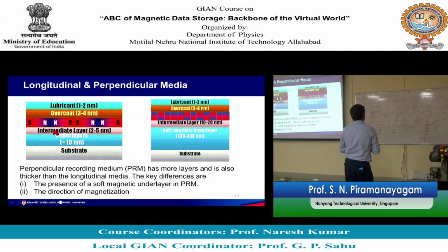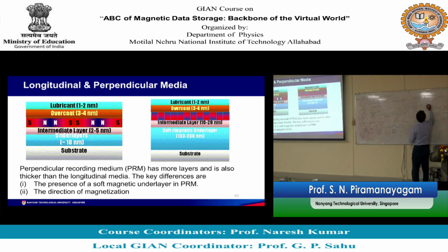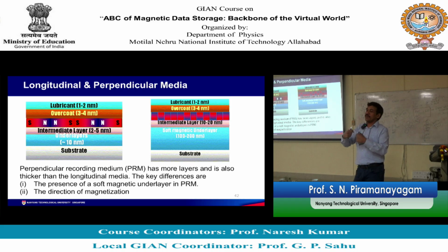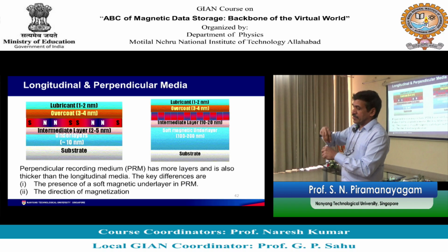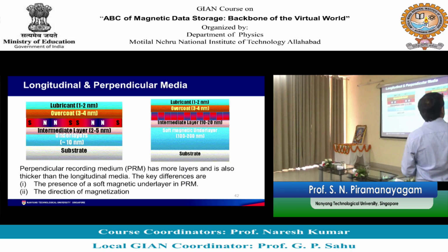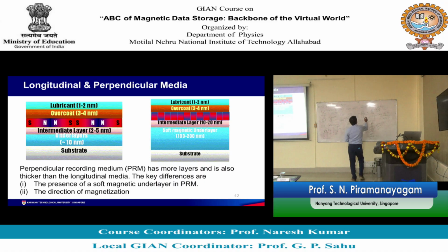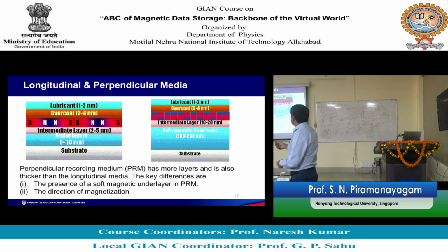Okay. So sometimes what happens, the chromium may have certain lattice, let us say chromium lattice parameter 2.56. I am just throwing some number, okay, maybe this is not accurate, and let us say cobalt is 2.42, something like this. Okay, there is a mismatch. So mismatch is like you have two Lego blocks, but the cylinders or holes are slightly not matching. So you want to improve the matching, what you do, you add some more layer, some intermediate layer with a lattice constant of say 2.50. Okay. So now you reduce the mismatch, then you make the cobalt grow on top of this.